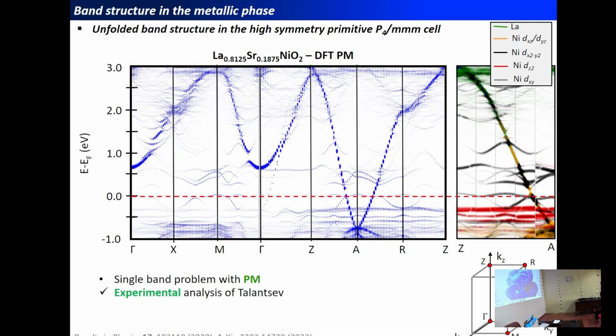And if we do the unfolding of the band structure in the primitive P4/mmm cell, which is the high-symmetry cell for the infinite-layer phase, we end up with a single-band problem dispersing around the Fermi level. And if we project this parabola on the different contributions, we see that there is no oxygen contribution, and it is effectively dominated by the nickel d states. And so this single-band problem that we observe with our paramagnetic calculation is in agreement with the experimental data analysis.